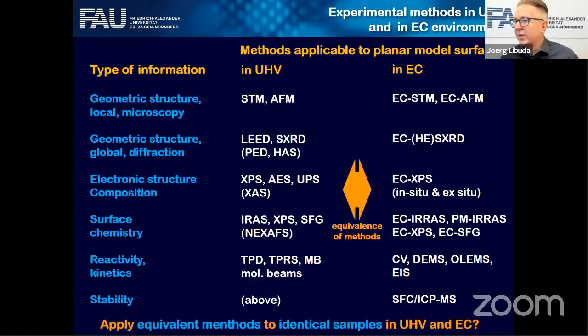So if you want to detect an unstable adsorbate monolayer on the surface, that would be very difficult with such an experiment, because you would immediately have chemistry. If you're just interested, for instance, in the stability of nanoparticles, the situation will be very different. You will not easily spontaneously dissolve the nanoparticles when you take out the sample. So again, I think this is tricky. In these experiments, we took the sample out, and the LEED pattern that you see, for instance, for the cobalt oxide is the LEED pattern where we do no post annealing. So the system is as it was in the electrolyte, and it's just dried. Of course, there's probably a lot of electrolyte left over on the surface. But that's what you can do.